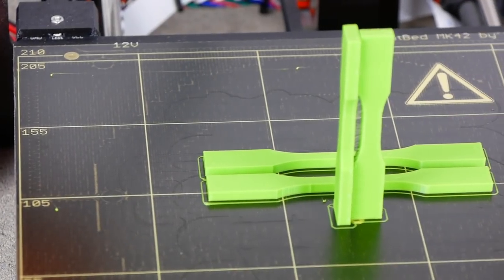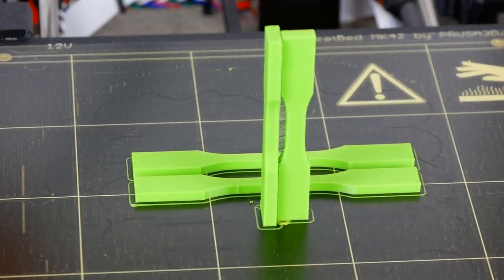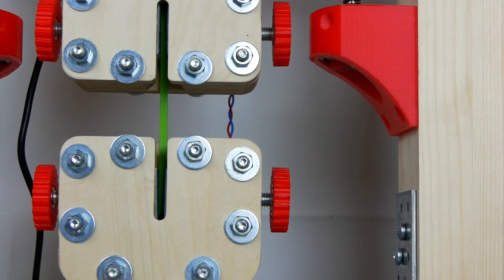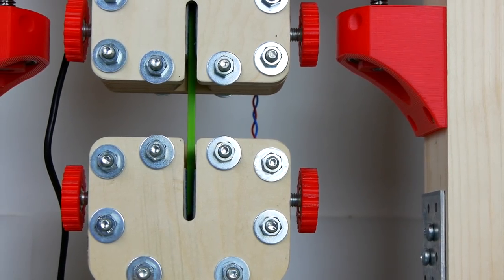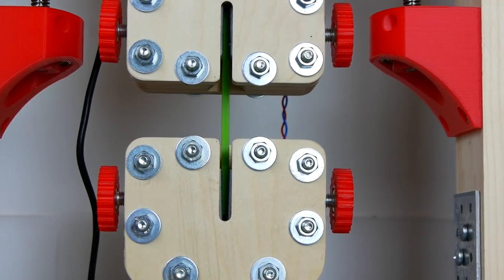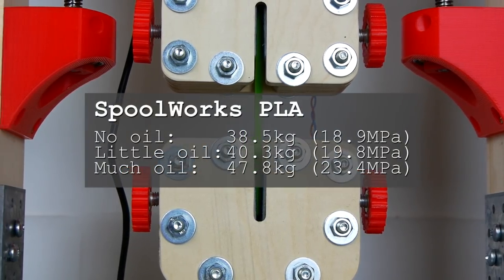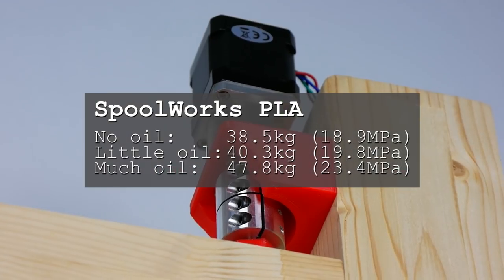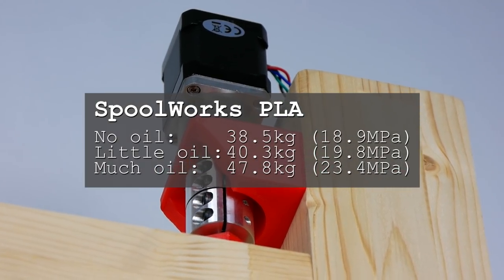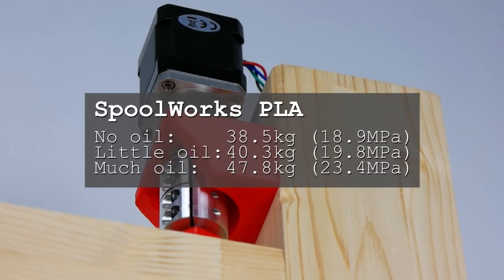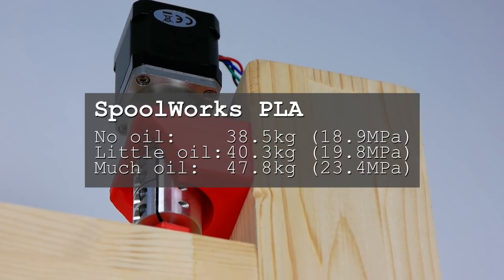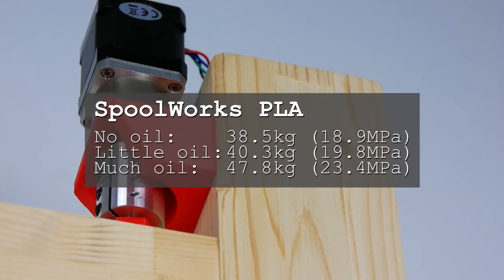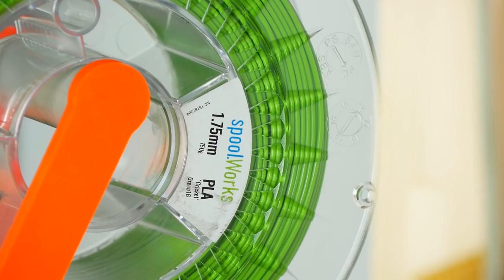Keep in mind that the specimens I am testing were printed out in an upright position so I am testing the layer adhesion. I tested them in my tensile testing machine and got results which really confused me. The strength of the specimens without oil was worse than with much oil. The strength of the parts with only a tiny amount of oil was similar to the strength without oil. So what went wrong? Can you really increase the strength and quality of your prints by using a filament oiler?